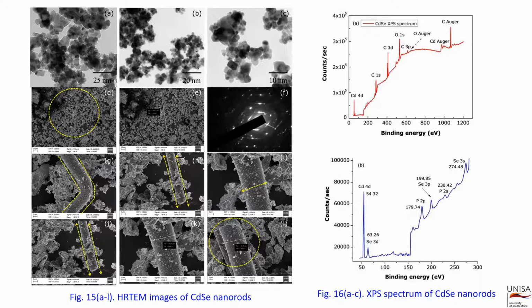From figure 15, HRTEM images of the cadmium selenide synthesized in this work show a good shape with a less pronounced stacking fault, with measured mean diameter and length of 25 nanometers and 50 nanometers respectively. This could be attributed to the reason that in low resolution HRTEM images,